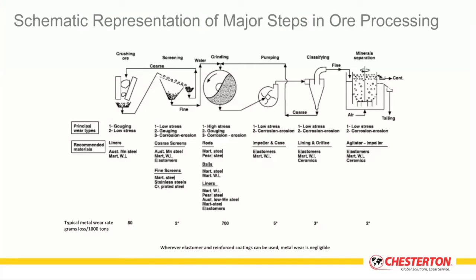In the very bottom section of this slide, you'll see there are areas where wear rates are quite high, such as the grinding area. This is where you have a lot of particle size attrition. There's large particles being crushed into smaller particles, being crushed into finer particles still, all as a process to liberate the valued ore product from the gangue or the waste product. There are slightly lower wear rates that you might see in the crushing phase. This is where you're doing primary crushing, getting it down into the size ore where you can grind and liberate. In the crushing phase, we're really not liberating ore, we're just breaking the large rocks down into those smaller ones.